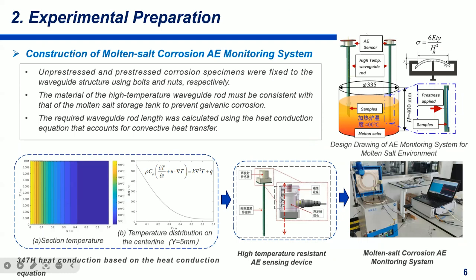And this is a design drawing. And we use a waveguide rod to reduce the influence of temperature, since the temperature is not very high for the AE sensors. The unstressed and prestressed corrosion specimens were fixed to the waveguide structure using bolts and nuts, respectively. The material of the high temperature waveguide rod must be consistent with that of the molten salt storage tank to prevent galvanic corrosion. The required waveguide rod length was calculated using the heat conduction equation that accounts for convective heat transfer.